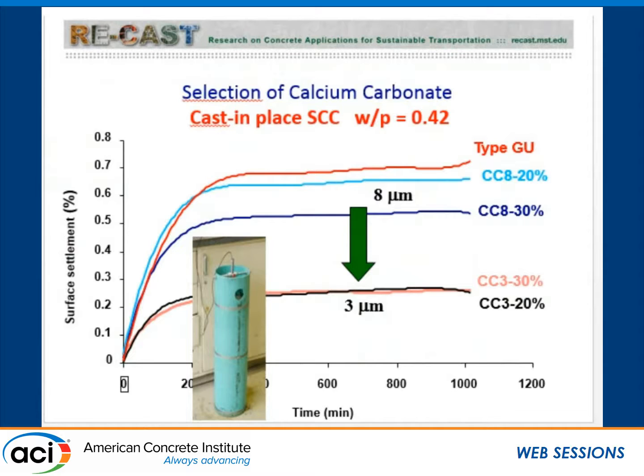And we wanted to see if indeed the use of the limestone filler has any effect on the stability. And one good test for assessment of stability of SCC is a surface settlement test. This is about a 3-foot column of concrete, 8 inches, and you put an LVDT and look at the settlement of the surface. And we see over here that for a cast-in-place SCC with a water powder ratio of 0.42, type 1 cement or a GU cement will have about 0.65, 0.7% settlement. And if you replace that by 20% or 30%, by mass, with the calcium carbonate that is medium fineness, it doesn't do much. It reduces the settlement a little bit.